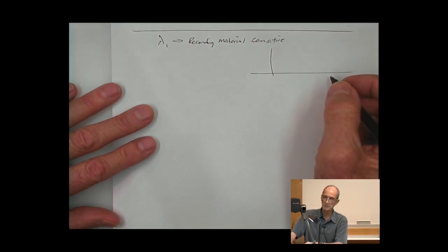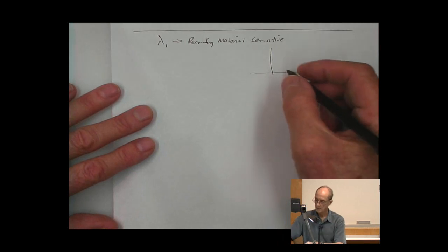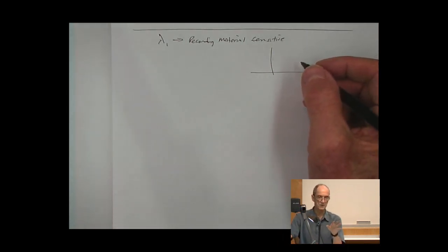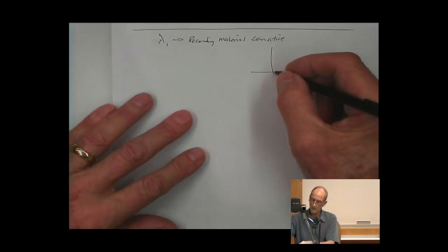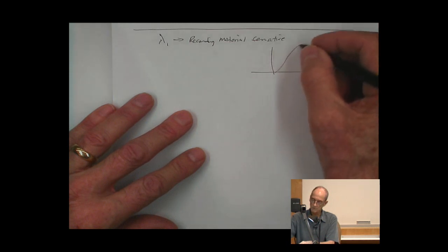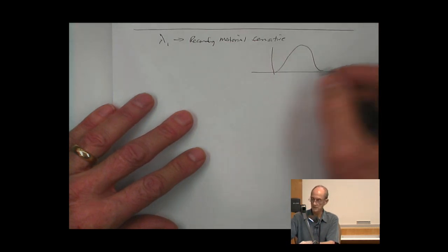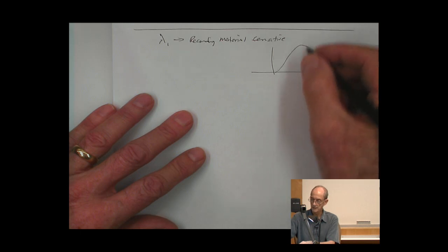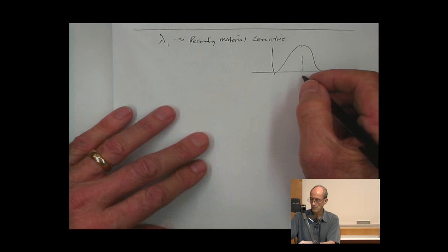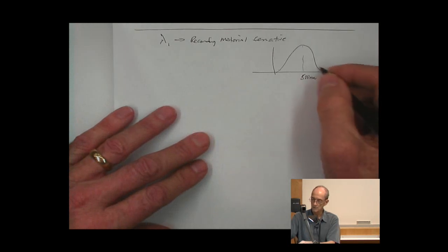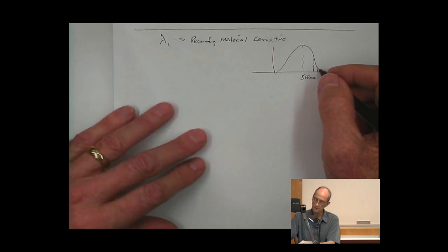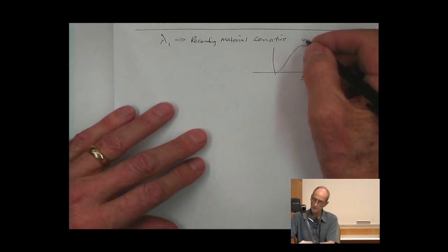Most of the photopolymers, the ones we have actually, were sensitized in the red, but a lot of materials that we work with, like dichromated gelatin, for instance, have a peak sensitivity around 500 nanometers. So if you use 514, it starts to fall off. 532, which is the doubled YAG laser, is pretty far down. 488 is very good.